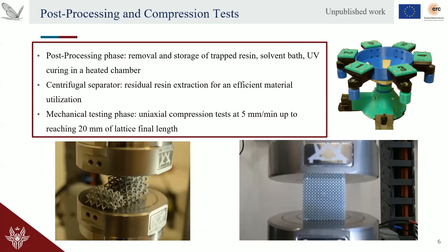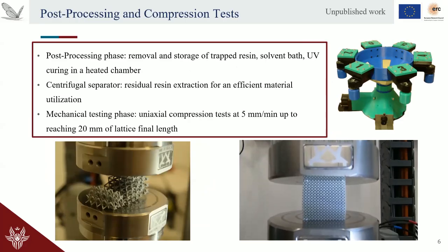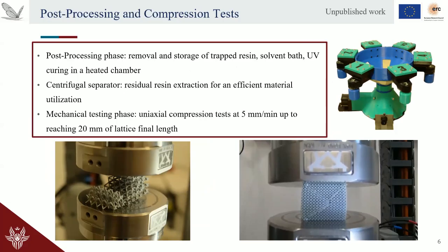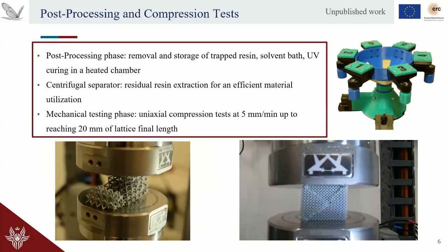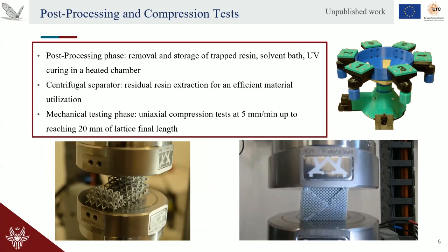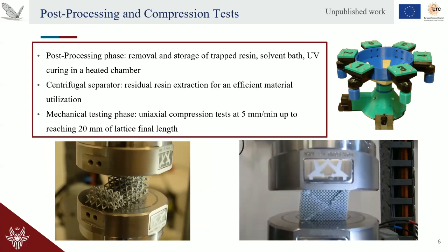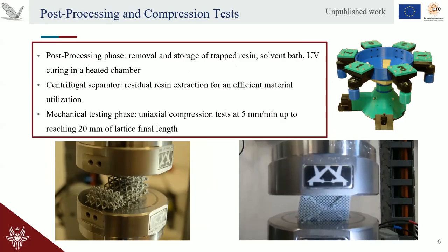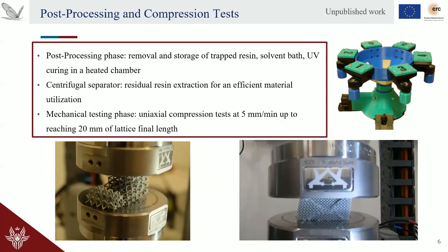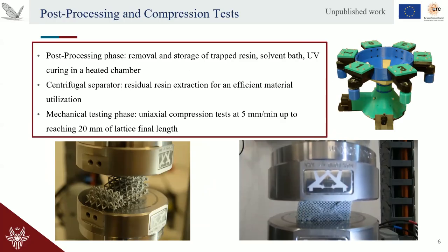After printing, just for completeness, since these specimens are very porous and we are dealing with vat polymerization, we have to properly separate the unpolymerized resin and solvent with a centrifugal separator. After separation, we have to post-cure them in a UV bath, and after that, we tested the specimens under a static test using a 10 kilonewton machine.